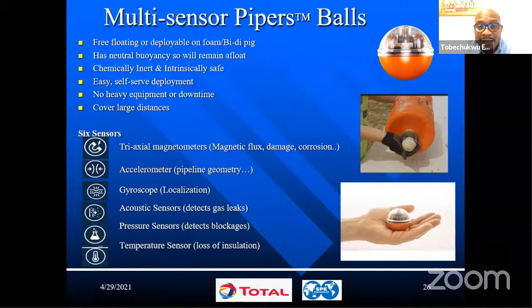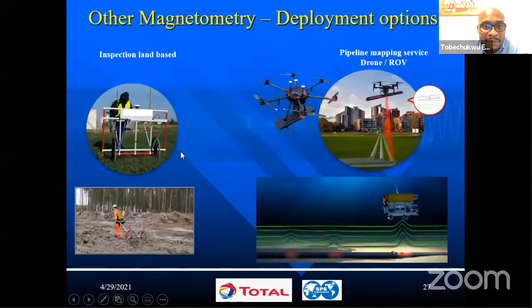If you have blockages or constriction in the line, the local pressure at that point will accelerate the flow, because of course the area has been reduced, but you have the same flow rate. So you have a quick increase in the velocity. And you can tell that you have a blockage there. And you have temperature sensors as well, which can help you know if your pipeline has lost insulation.